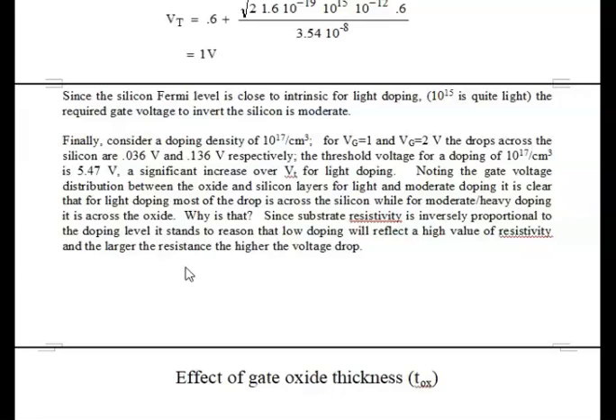Oh, one more thing we should calculate before we go explain that. The threshold voltage is huge. It went from 1 volt, it catapulted itself up to almost 5.5 volts. And again, that is indicative of the fact that for the heavy doping, the Fermi level is far away from intrinsic, 0.42 eV, rather than the 0.3 eV for the light doping. We have much further to go to invert the substrate. And that's why the threshold voltage is so high.